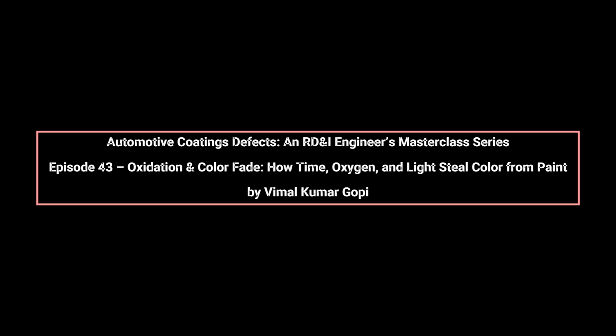Additives play a central role in delaying oxidation and fade. UV absorbers intercept high-energy radiation, while hindered amine light stabilizers neutralize free radicals. Their effectiveness depends on long-term retention within the coating. Migration to the surface, leaching during washing, and chemical consumption gradually reduce protection, making fade inevitable over extended exposure.